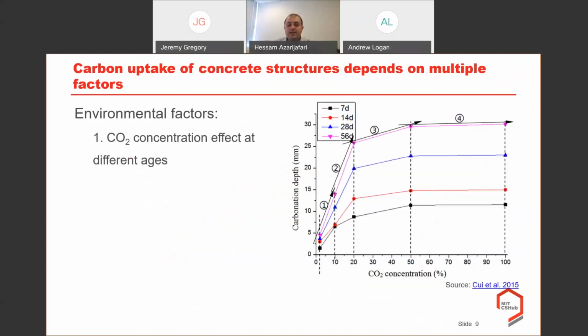The next one, after talking about the curing and alternative binders and water to binder ratio, is the environmental factors, more specifically the CO2 concentration that can affect the carbonation depth at different ages and at different CO2 concentrations. Here is a study that you can see from this graph. The CO2 concentration increase from 3% up to 20% can significantly increase the carbonation depth at different ages of testing, from 7 days to 56 days.